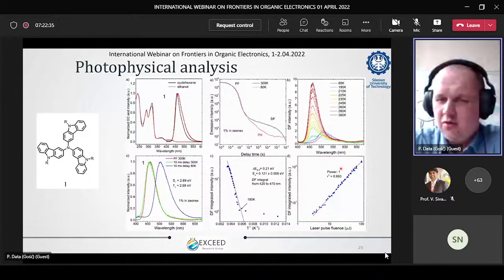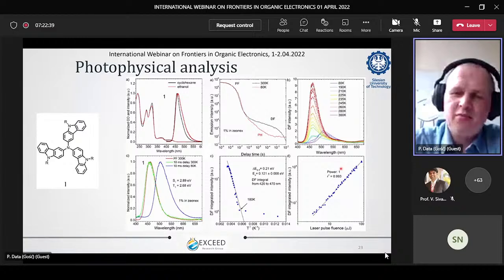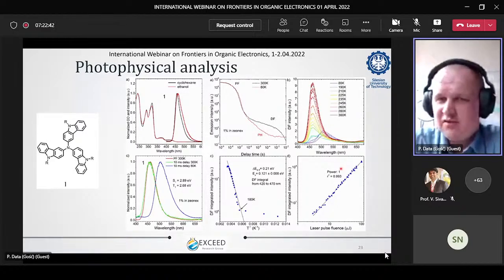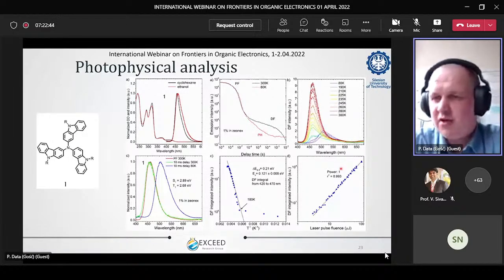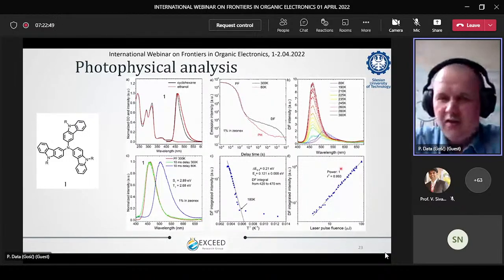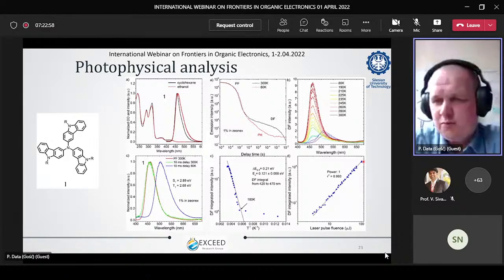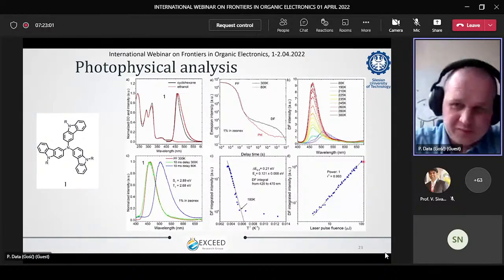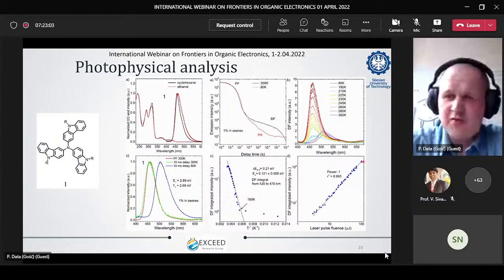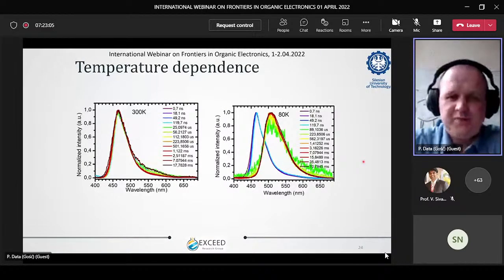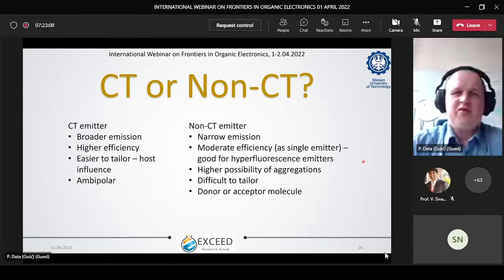If the value is close to 2, it means for two triplet states we get one singlet state, which means we have a TTA process. In many cases, when you analyze your molecules, the value is between 1 and 2, like 1.5 or so. That means we have mixed emission, because it happens as well. But without this analysis, we cannot directly prove that we have a TADF process. So that's one way of doing that.